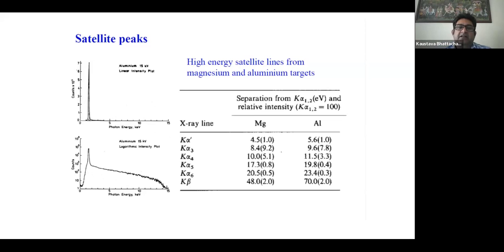So as I have told, in the XPS system my source was an X-ray source, and basically the X-ray source should be of a particular element. For XPS, we use as a lab source either aluminum K alpha, magnesium K alpha, or silver L alpha. These are usually the sources that we use. If we are not using a monochromatic source, we are usually using a dual anode source. And in a dual anode source, we know that there are two anodes side by side with a separator,